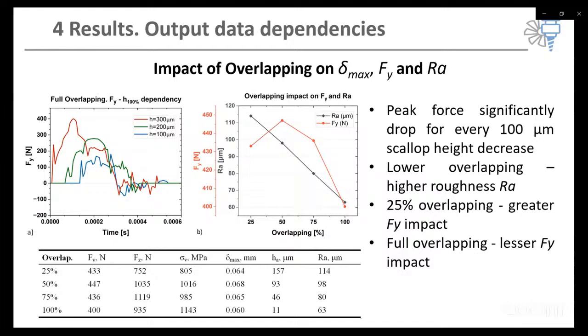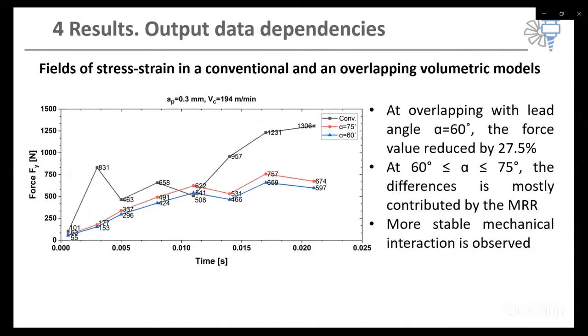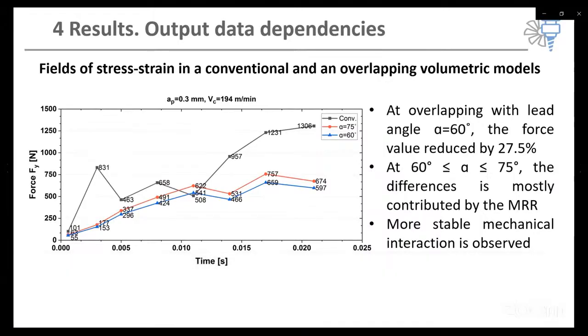The graph can be divided into three parts: an increase in the horizontal force component Fy, slow down, and decrease. This behavior reflects the relationship between the resistances generated by the immersion regions and the tool cutting edge. At full overlapping, the Fy force was 27.5% lower compared to the conventional method. This showed the effectiveness of overlapping in reducing the stress on the wall.